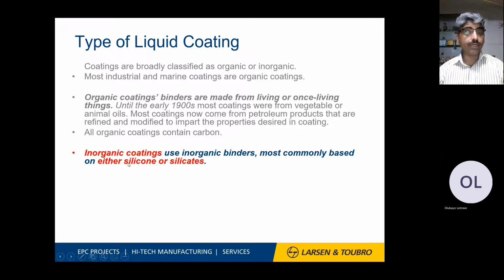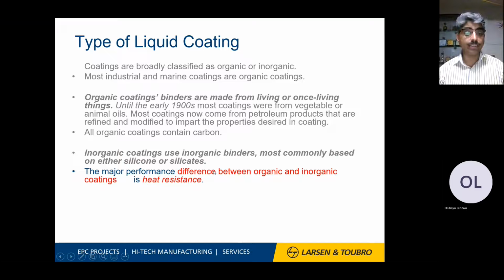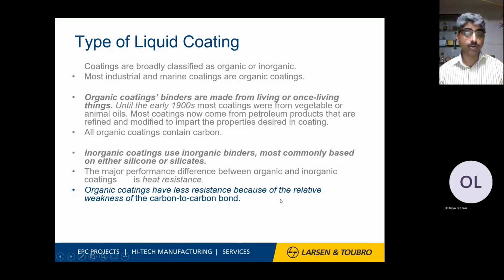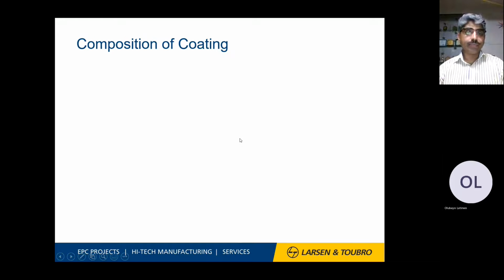Inorganic coatings are more popular in oil and gas, having a binder most commonly based on silicon or silicate. This is the base by which the paints are known, their name, silicon base or silicate base. The major difference between organic and inorganic coating is the heat resistance. What I say is that inorganic has more heat resistance than organic coatings. Organic coatings have lower resistance because of the relatively weak carbon to carbon bonds. Because of that, it is normally good for low temperature applications, whereas inorganic coatings have more applications in oil and gas applications.